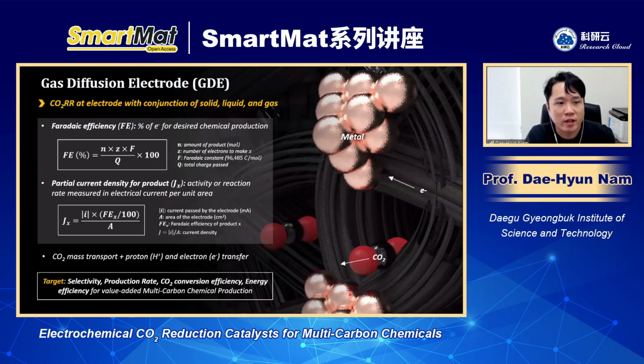So if you look at this in more detail, there are maybe five important metrics from the CO2R performance point of view. First, we need to think about the Faraday efficiency, which is mostly related to the product selectivity. And this is a performance metric familiar to us. And if we have the chance to solve this selectivity issue, then we need to move on to the production rate or productivity. And this can be quantified by the partial current density. It means that if we apply the current density to the Faraday efficiency, then we can get the partial current density. And this partial current density means how fast the production rate is that we can achieve.